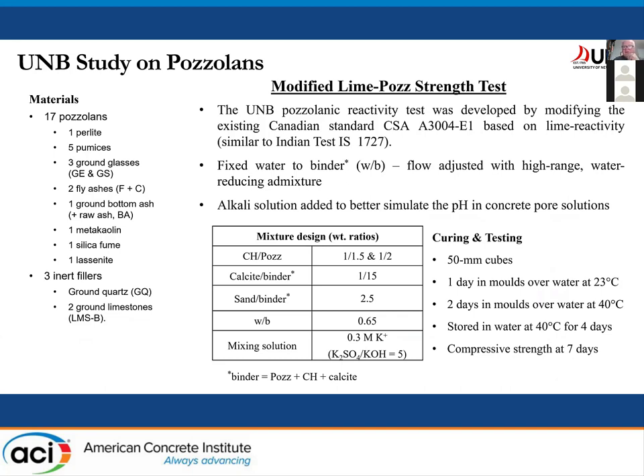And so in this case, what they did, they took a lime pozzolan test that's in the Canadian standard. It's actually in the Indian standard as well. It was an old test, removed from ASTM in the 1980s because people didn't think it was that good, but we've modified the test method here. So you've got a different ratio of calcium hydroxide to pozzolan, a small amount of calcite in there, a sand to binder ratio, and the water to binder ratio is fixed as opposed to a constant flow.